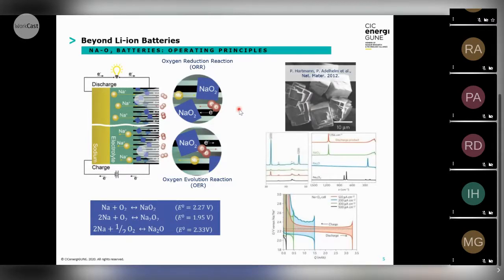So the first study reporting a sodium oxygen battery at room temperature was performed by Philipp Adelhelm and his group. And they saw nicely how you can discharge a battery and form these sodium superoxide cubes on the surface of that air cathode, which was analyzed by means of NMR and XRD to prove that it was this material, sodium superoxide. Here we can see that the charge potential is quite low, and this was the first study showing that these batteries might be better on charge, unlike lithium-air batteries known until that time.